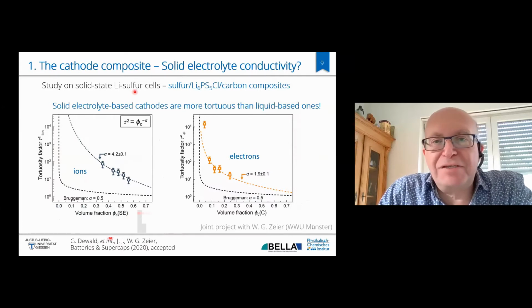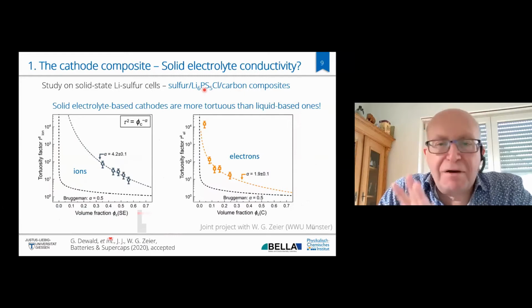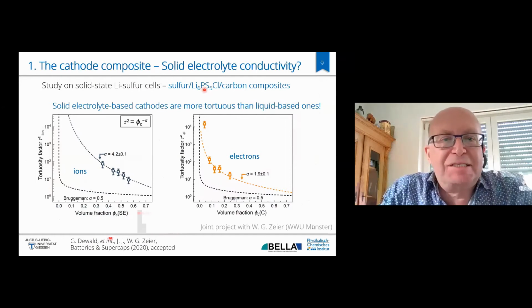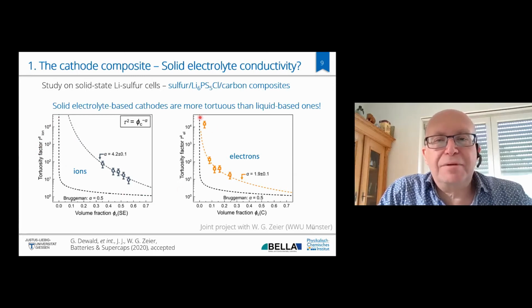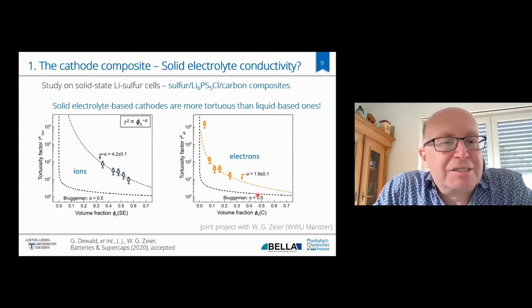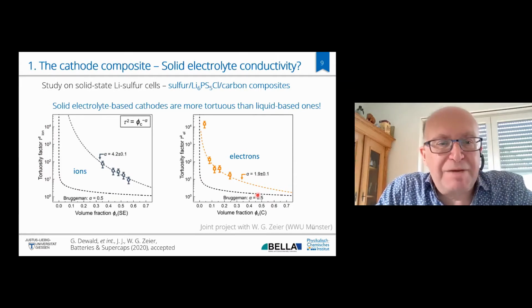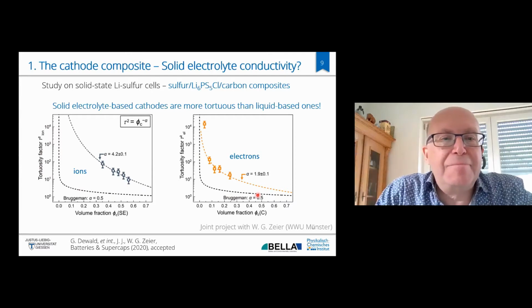Now, solid state lithium sulfur cells have a cathode composite of sulfur mixed with a solid electrolyte, which in this case is an argyrodite material, and carbon. So this three-phase composite, which of course also still contains some porosity, is being studied in solid state batteries. And what you see here is the tortuosity factor. This is the Bruggeman relation, which is a relation for describing the tortuosity of spherical particles in a matrix. And you see a relatively low tortuosity environment. And if you go to a solid state with a solid electrolyte, the tortuosity becomes much higher. This is for ions and this is for electrons.